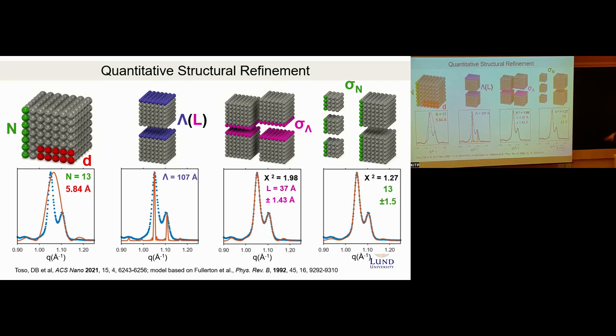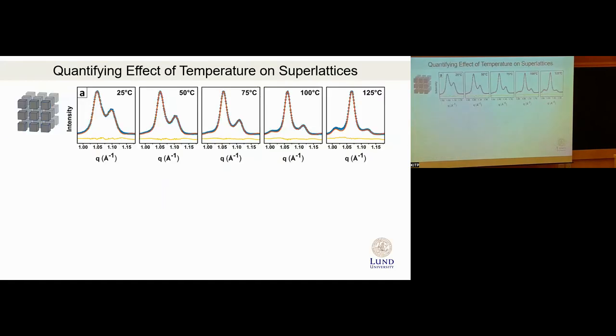We can perform all this in Python, and for a given sample of perovskite nanocubes, we can quantify average size of nanoparticles, 13 planes plus or minus 1.5, interparticle separation and its fluctuation, and then back-calculate the superlattice constant. So why is it useful? One illustration: we start heating these superlattices. We first vacuum them to make sure the sample is stable, at least that there is no obviously trapped solvent. Then we start heating it, keeping it for 15 minutes at each of these temperature set points, and see how this Bragg peak evolves. It obviously evolves, becoming sharper, and the structure changes.